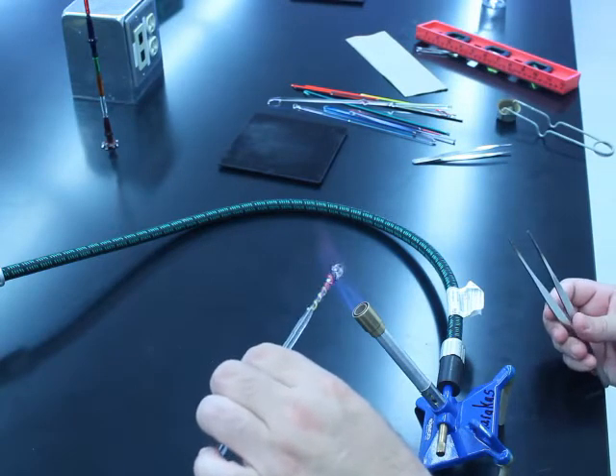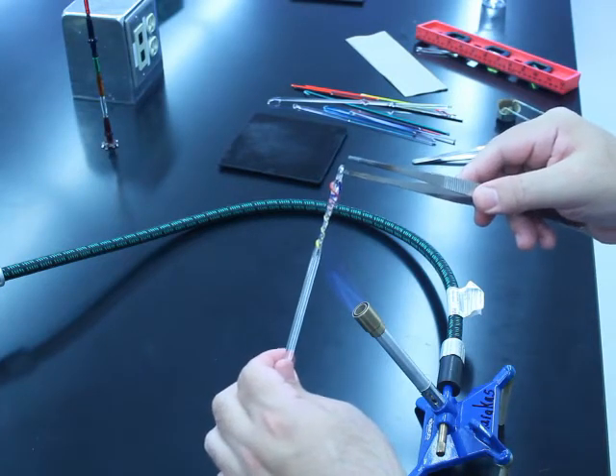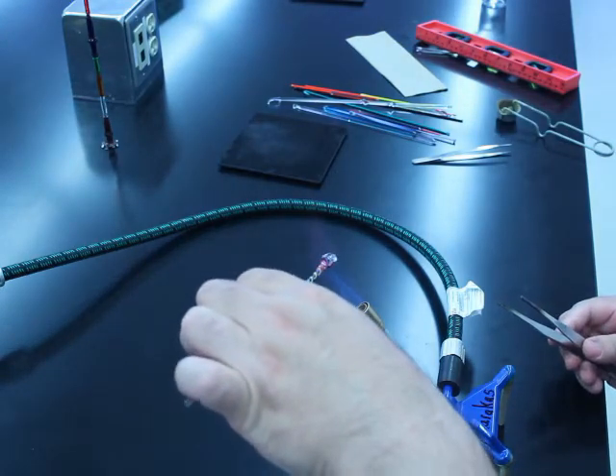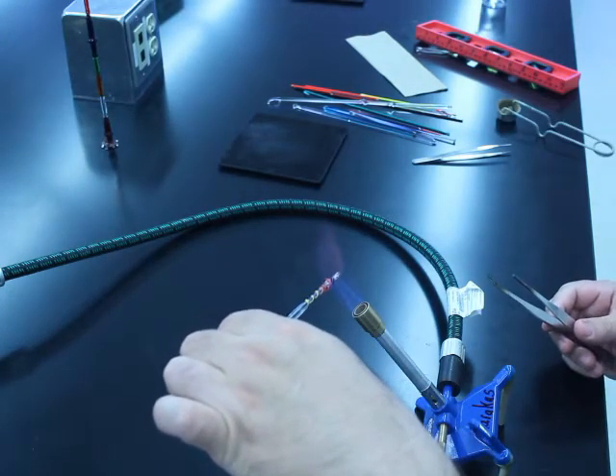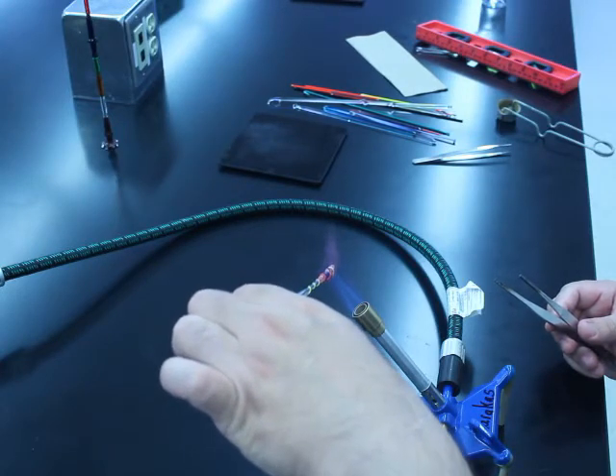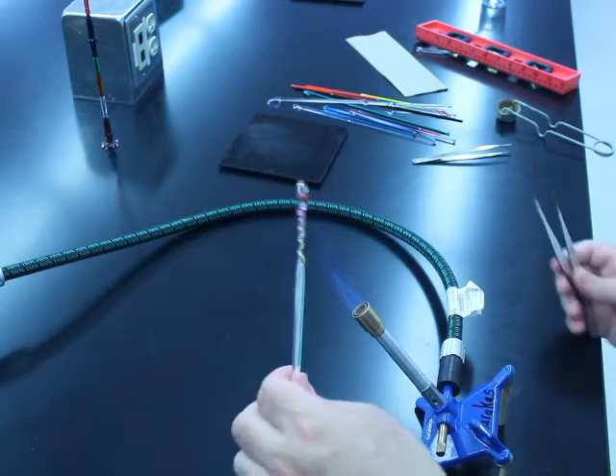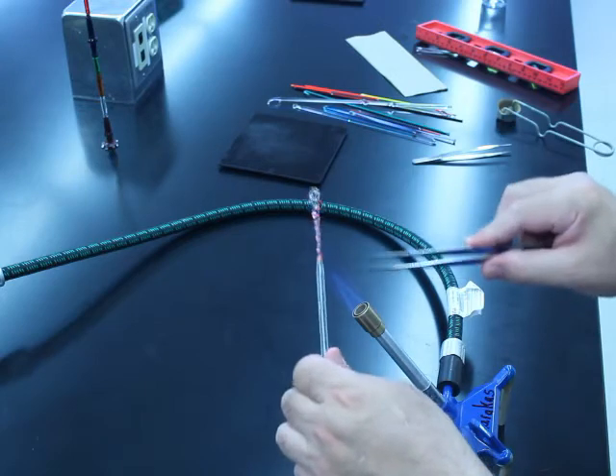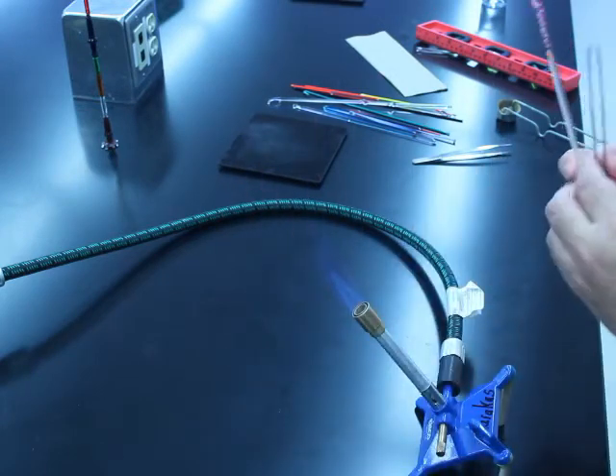I don't have one with me, so I'll show you a trick — take your tweezers on the inside and give it a little push like that. Since I touched it with metal, it cools down rapidly, so I definitely want to heat it back up to remove any metal marks or chill marks from touching with the metal. Notice how this has turned yellow, and that's because I haven't heated it in a while. Paying attention to the colors is very important to understanding the temperature with some of these glasses.